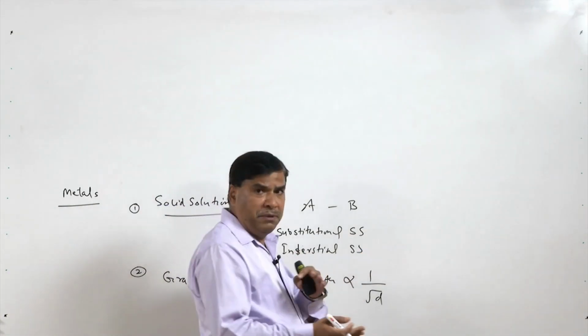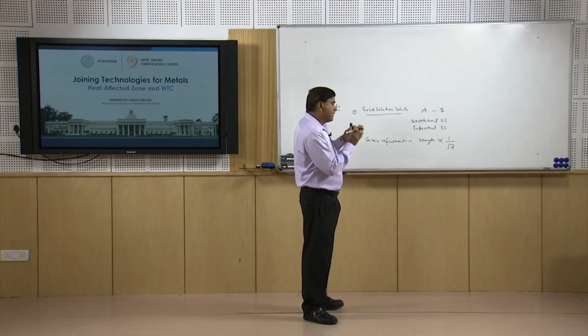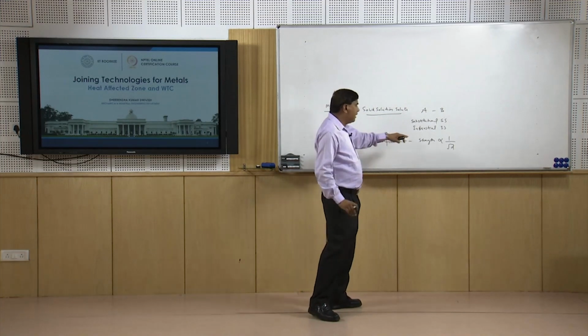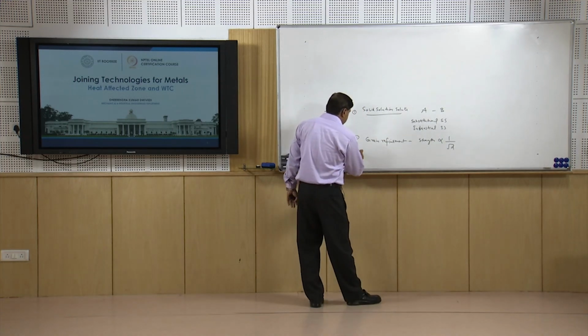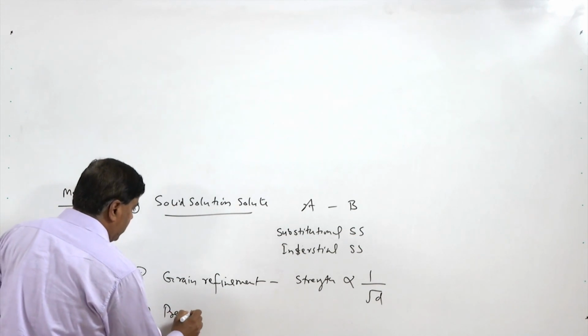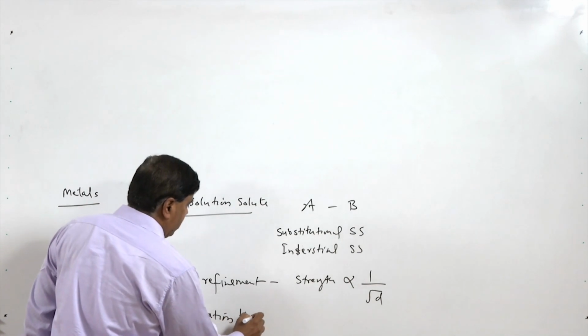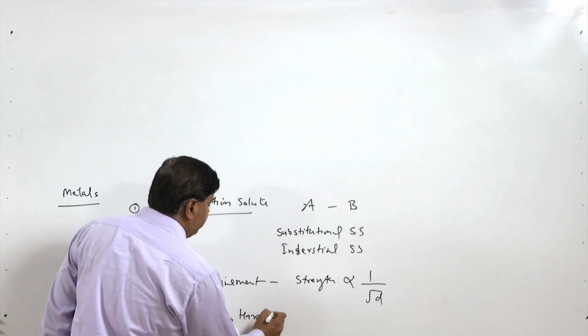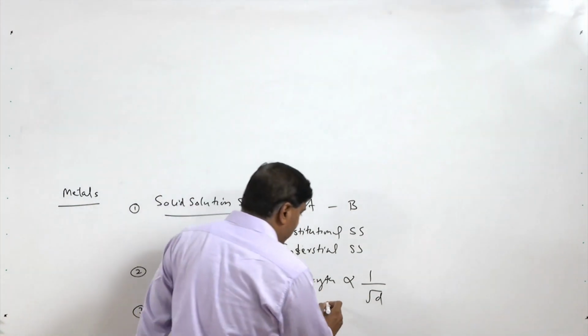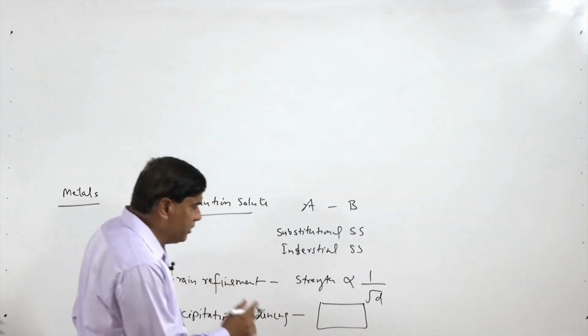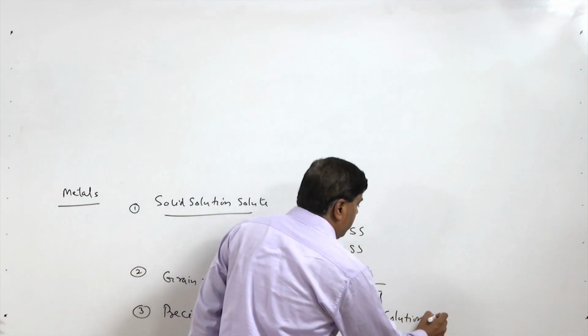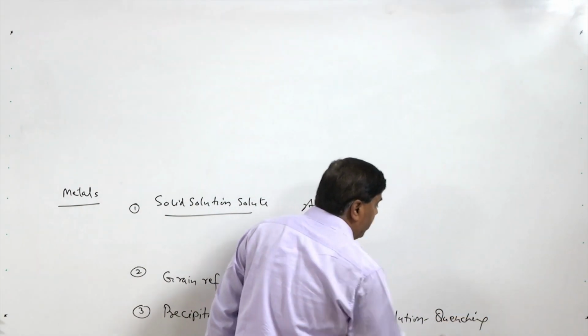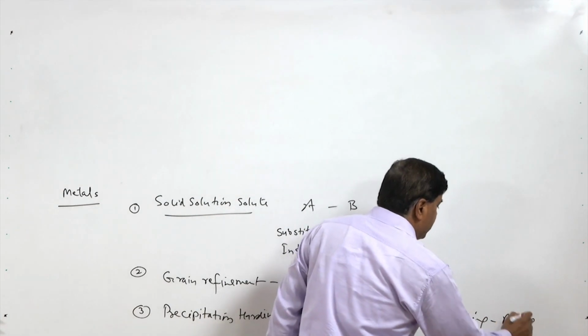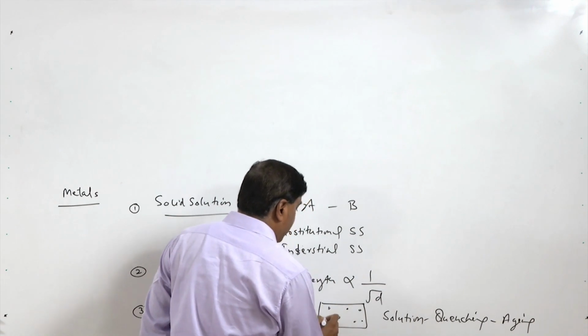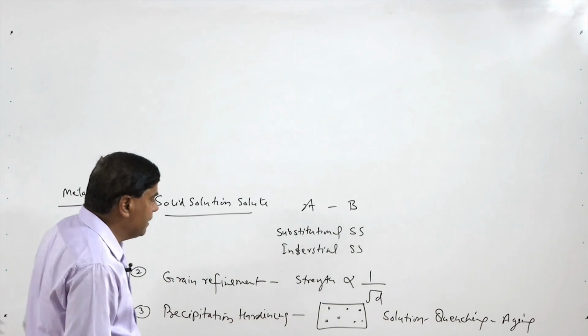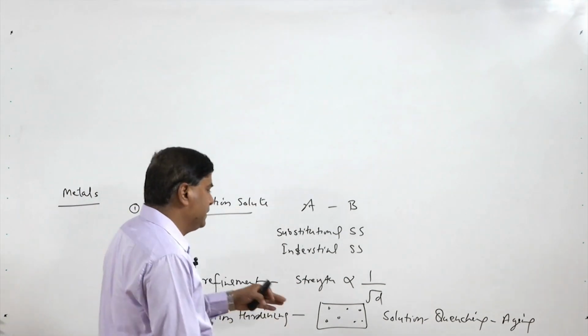So, whatever factors increase the grain size, either in the weld or in the heat affected zone, will lower the hardness as well as the yield strength. Third is precipitation hardening. In this mechanism, whatever alloying elements are there are dissolved in the solute through solution treatment, followed by quenching, so that a supersaturated solid solution is formed, and then aging is undertaken. During the aging, the precipitates are formed here and there, and they strengthen the material by forming precipitates in the matrix of the metal.